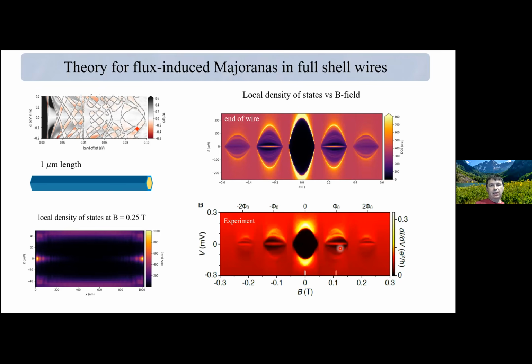What is remarkable actually is the resemblance between simulations and experiment. These simulations are not fine-tuned to the experiments. We used some realistic parameters that we know, and these parameters have been measured independently. But if you put everything together, then we find that indeed the experimental data looks similar to the Majorana scenario.